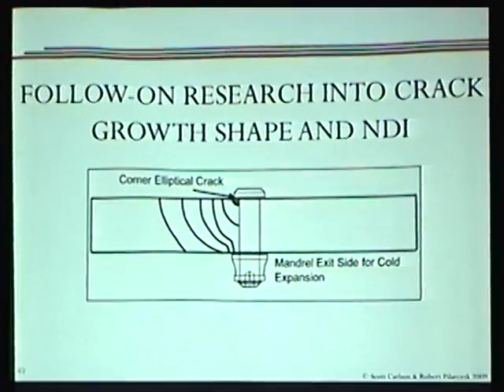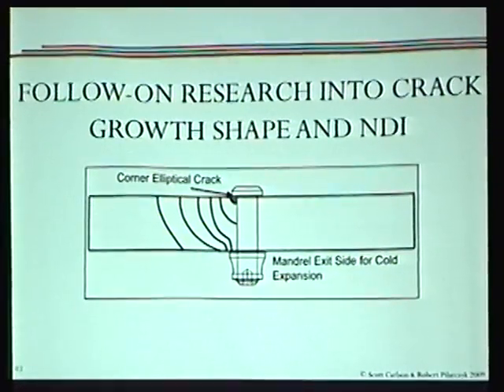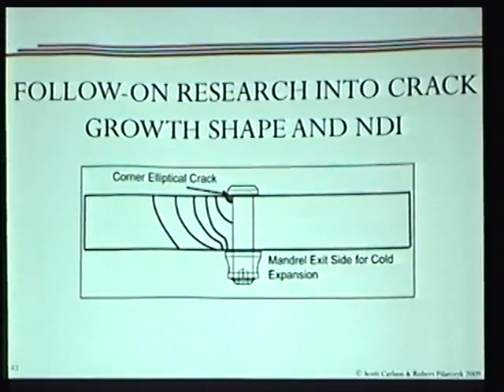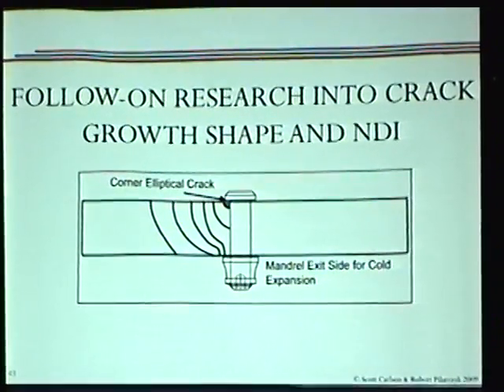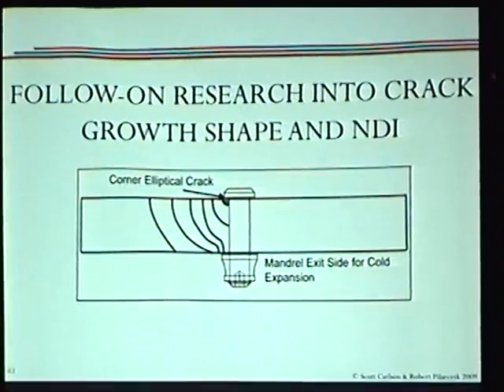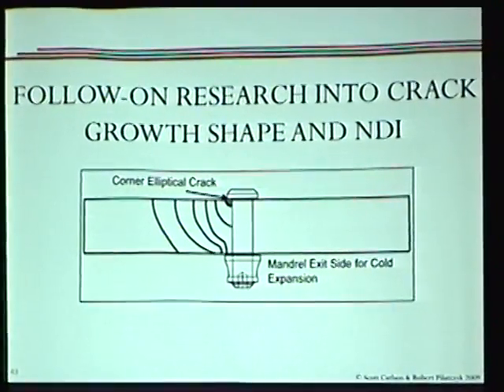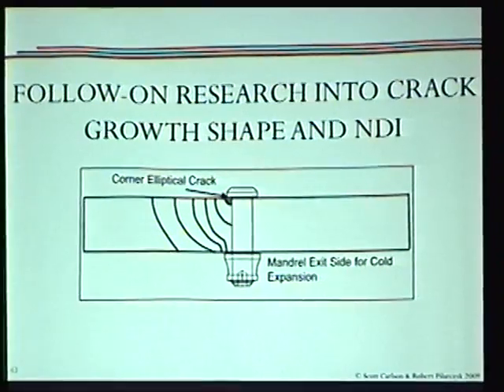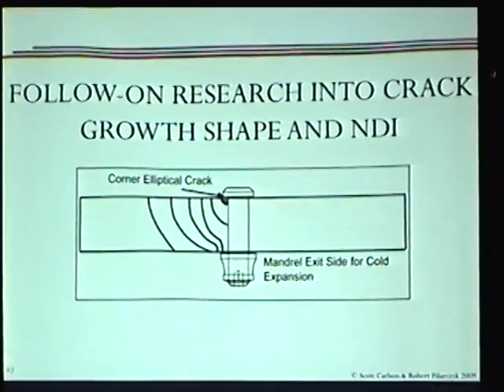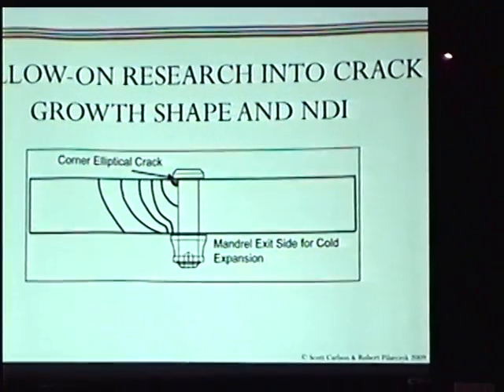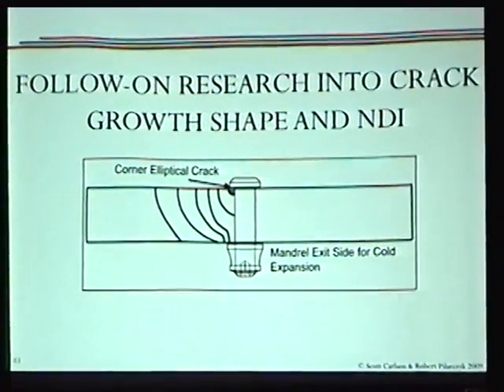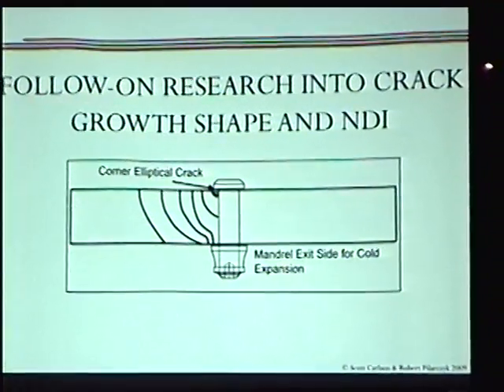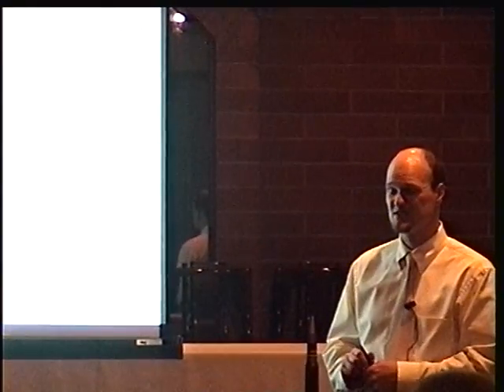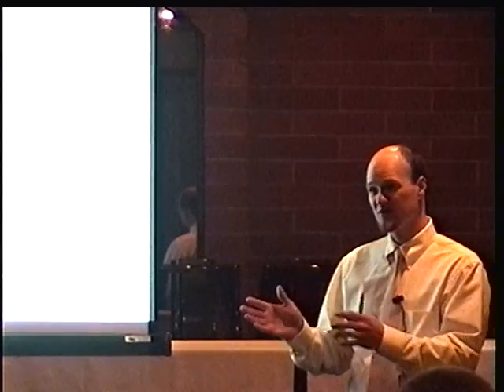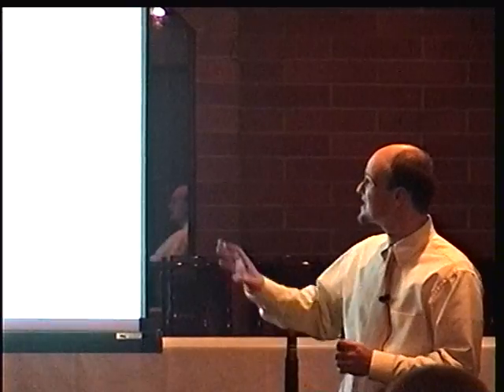And we worked together, and we do a lot of bolt hole eddy current inspections on the A-10 and different aircraft. We were really concerned about this unique crack front shape, the residual stress closing the crack, all these things coming together to change our probability of detection and our detection threshold if the hole is cold worked. What is the effect? So what we're going to do is we've got a bunch of specimens we're going to test. We're going to run them for a bit so that we grow a certain size crack in them, and then we're going to hand them over to Ward. He's going to do some NDI inspections. He's going to tell us, well, this is what size cracks you have.